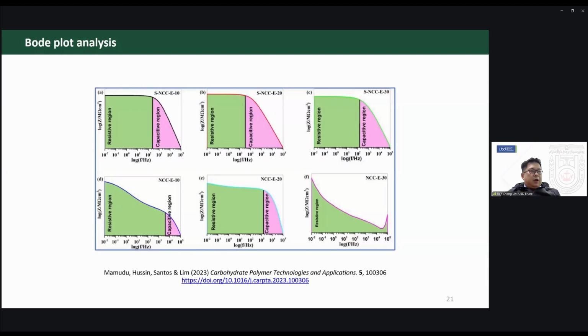So at low frequencies here, you see that the resistive regions give a clue as to whether there's coating delamination, and the increase in the resistive region is also an indication of delamination, which we actually saw occur more in coatings that have the nanocellulose. With the sulfated ones, you don't see so much.